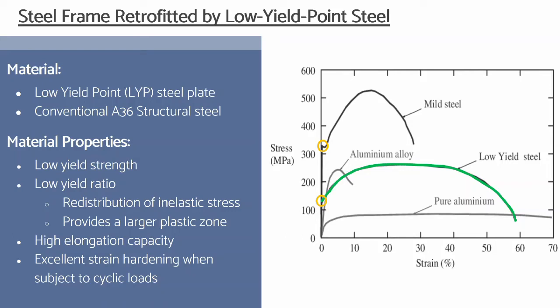The yield strength is less than 0.5 times the ultimate strength, and the much prolonged strain hardening process accompanied by the accumulation of plastic deformation will contribute to the seismic resisting capacity and guarantee the required lateral stiffness under earthquakes. With a Young's modulus of 210 gigapascals, the elongation at break is approximately 48%, and the favorable plastic capacity without deterioration will ensure the superior structural ductility. Attributable to its high plastic deformation capacity, the shear walls are able to maintain stable up to 3 to 6% of story drift angle. So the LYP steel has been widely applied in seismic engineering.